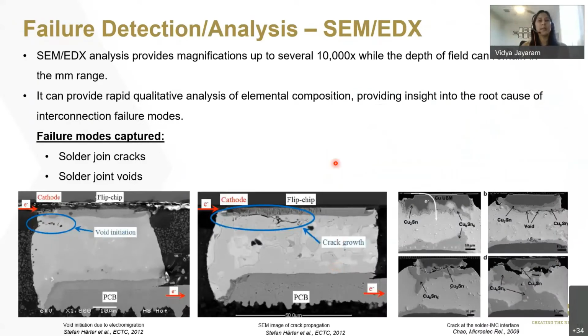And SEM combined with EDX is another very effective method to capture defects. And this method, even more so than capturing defects, gives us a lot more insight about what is actually going on. And this can help us figure out what the root cause of that failure was to begin with.